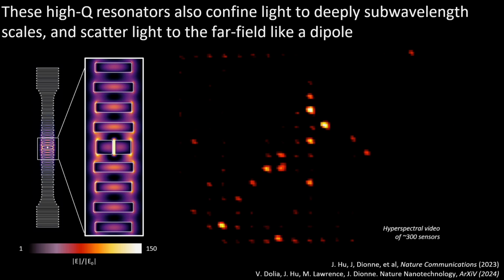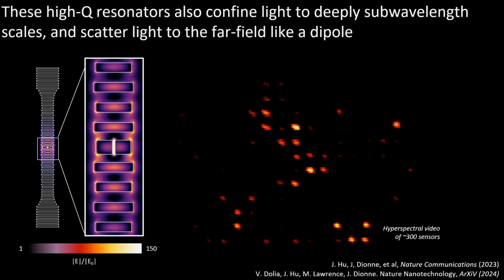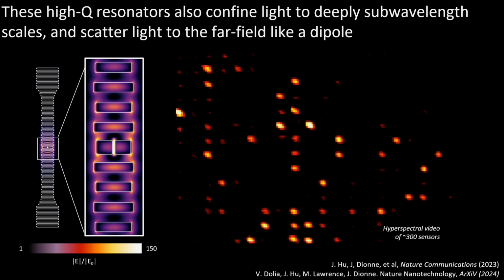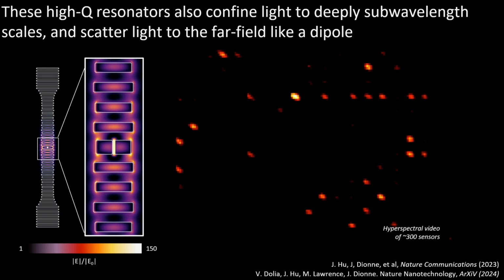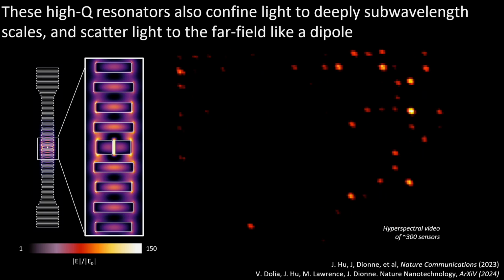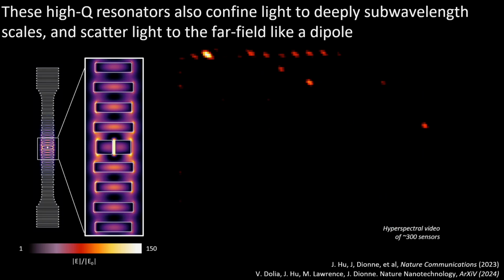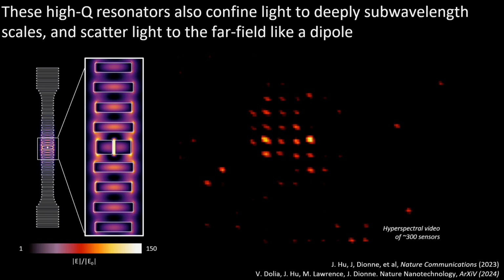And then here's a video of the sort of experimental data we get. Here we have about 300 sensors. We're just illuminating them in the near infrared, and you can see each of them is basically lighting up at different frequencies. So we're scanning the frequency of detection. You can think, okay, as we have different molecules landing on each of our sensors, we're collecting a distinct Raman spectra from each of these resonators.